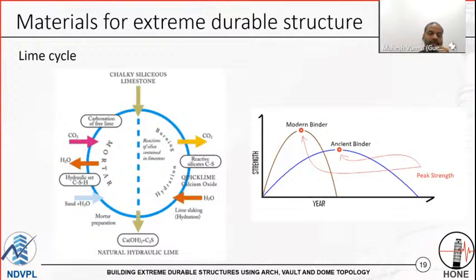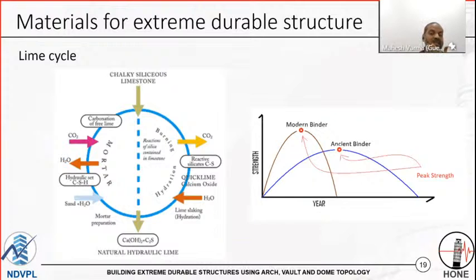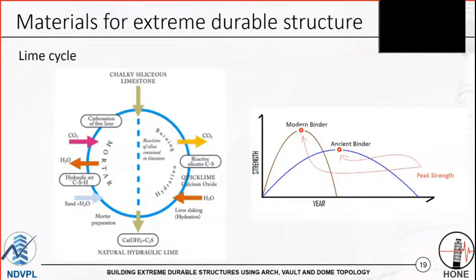Secondly, as you can see, when lime sets, it releases H2O. And H2O is required for the silica part, for setting, because it's a natural cement. So the water which is required for curing of mortar is readily available, released by lime. In turn, it works as a self-healing material. So when the construction is finished, if you observe some minor cracks, in 3 months you will observe that the cracks have vanished. I observed it on my sites many a time, practically.